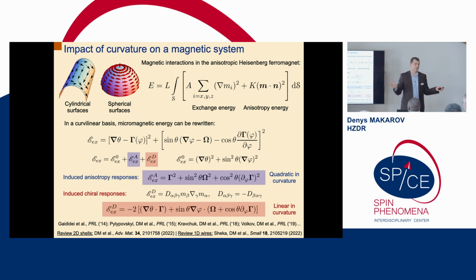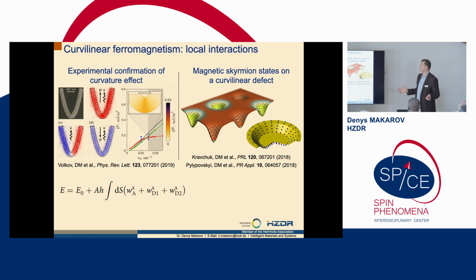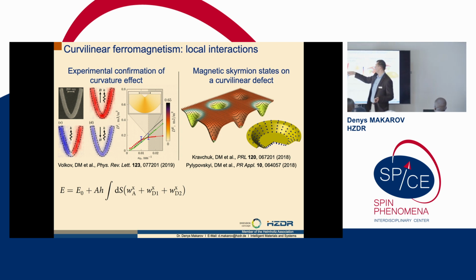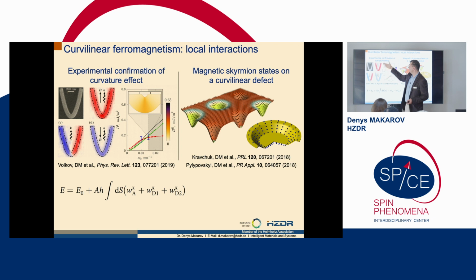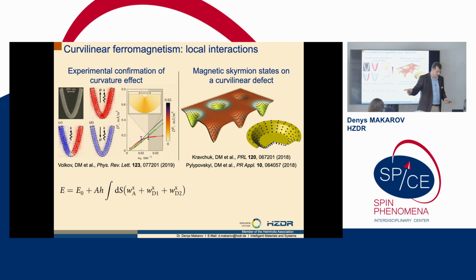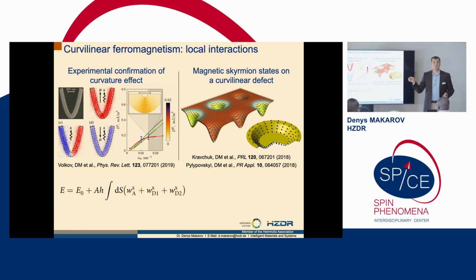But in semiconductors, they would call them differently, okay? But otherwise, we will have exactly these two things. And if you know about that, a lot of things become very, very simple. Because, for example, you can easily understand that if you have your ferromagnetic stripe, it's just a permalloy, 20 nanometer thick permalloy, you just bend it a little bit here, and you will have a curvature gradient. And the curvature gradient will pin the domain wall, and not only pin, but it will select the chirality of this domain wall. So it means that the sense of rotation will be simply defined by the direction in which your magnetization is pointing here. As simple as that.